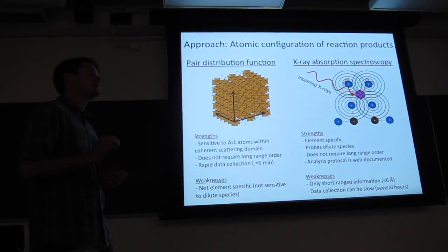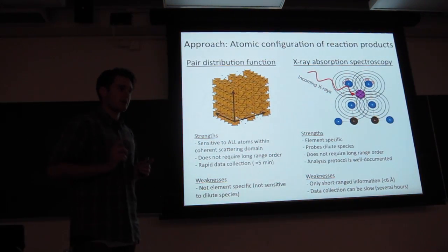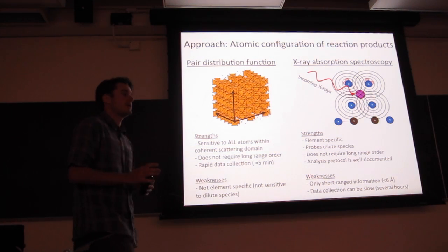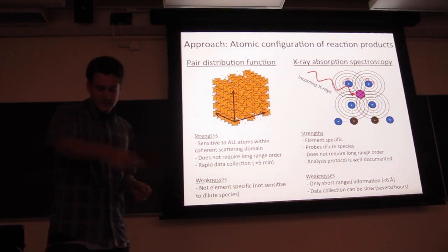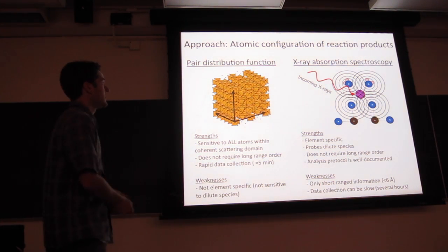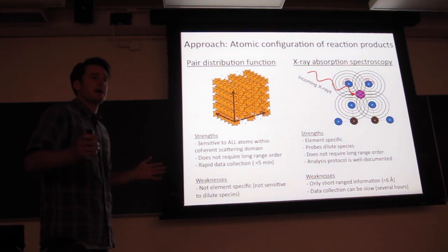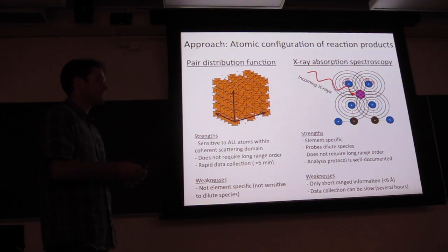But the problem with XAS is that it cannot see atoms past about 6 angstroms. So you're limited to the local coordination environment of arsenic. So it can only see what it's around for 6 angstroms. The PDF sees every single atom within the structure.